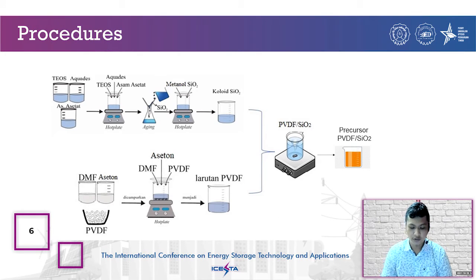In the next section, I will show you the procedure. The PVDF SiO2 precursor requires two main solutions, namely PVDF solution and colloidal SiO2. The colloidal SiO2 was prepared using the sol-gel method by mixing tetraethyl orthosilicate with acetic acid and distilled water as a solvent. The resulting colloid was then allowed to stand for 2 hours. Furthermore, the colloid was filtered and the precipitate was washed with ethanol to form SiO2. The precipitate was dissolved with methanol to produce 3000 ppm SiO2 solution.